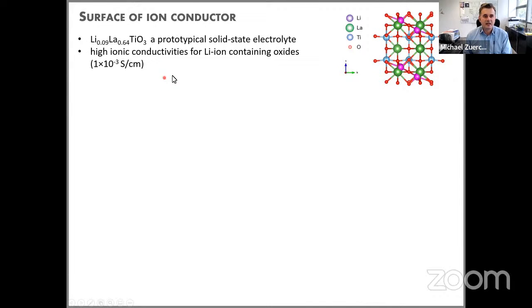One more example I want to show that we recently completed, submitted as a paper and should come out soon, is we measured the surface of an ion conductor. So we went back and thought, okay, what can we do with our capability of measuring lithium so nicely? We looked at a solid state electrolyte, lithium lanthanum titanium oxide, or LLTO for short. LLTO is an ion conductor. It's one of the candidate materials for all solid state batteries, where LLTO would be the electrolyte. You combine it with a cathode and you have a solid state battery.